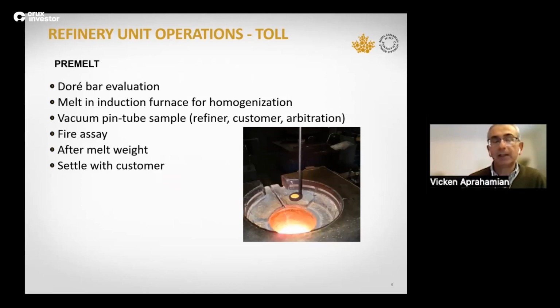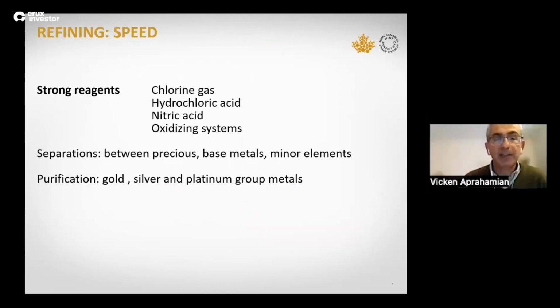The sample is then sent to a laboratory, and the fire assay technique is used to evaluate the precious metal content. The molten metal is cast after melt weight is taken, and then there's settlement with the customer before moving on to the refining stages. In refining, speed is of the essence. At the toll refinery, you don't want to hang on to too much precious metal. You want customer material to go through the system rather quickly. So very strong reagents are used: chlorine gas, hydrochloric acid, nitric acid, oxidizing systems in general. The separations between precious metal, base metal, and minor elements happen quickly, and then there's a final step in purification to obtain the gold, but also silver and the platinum group metals.